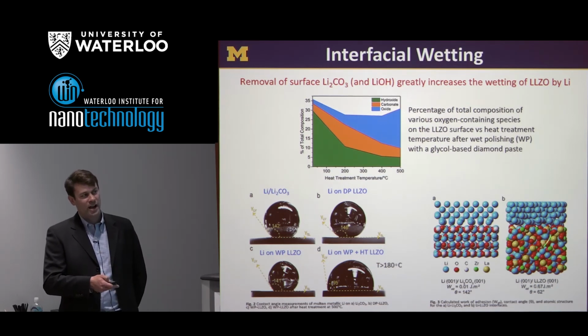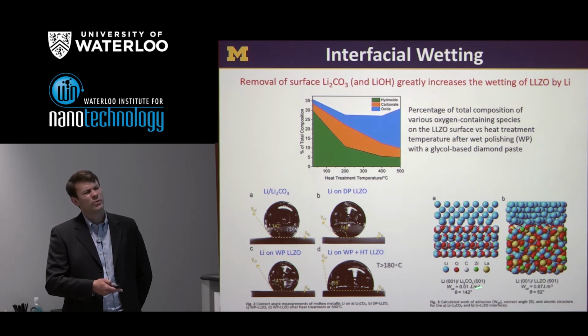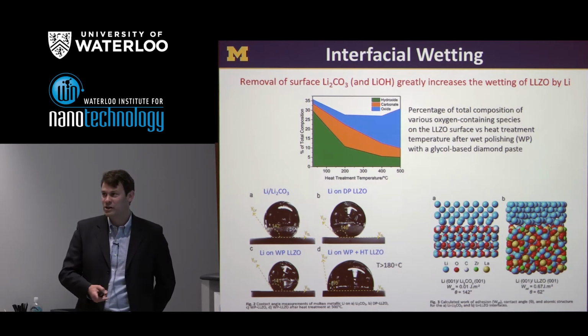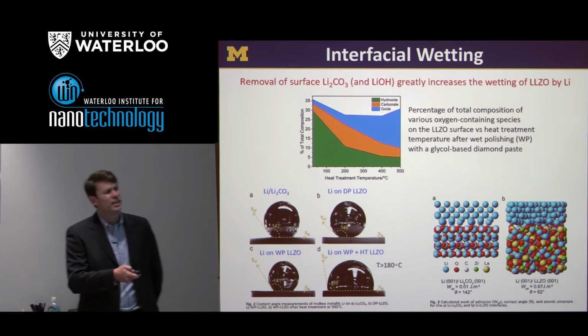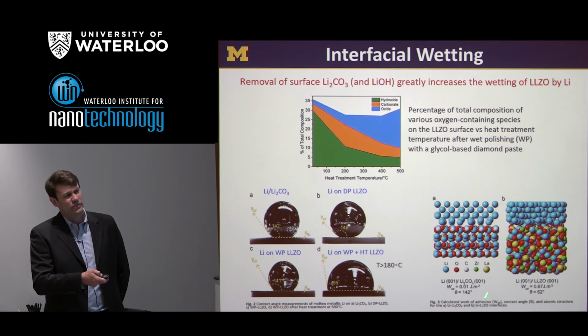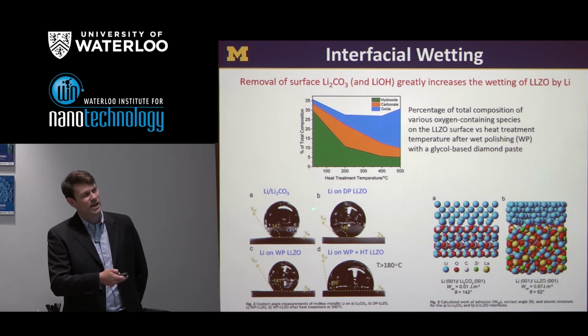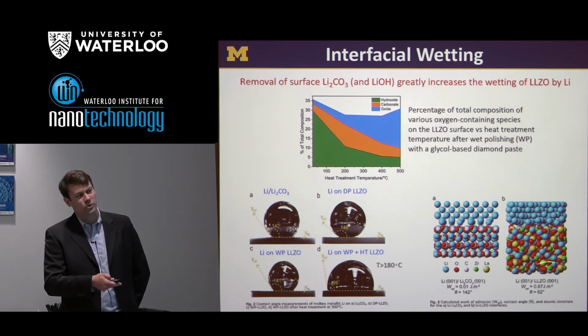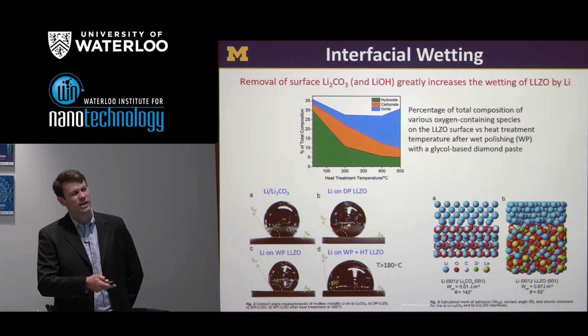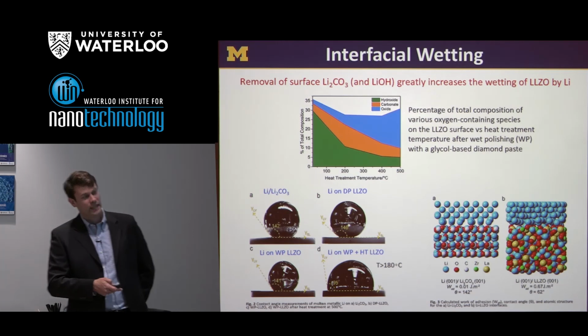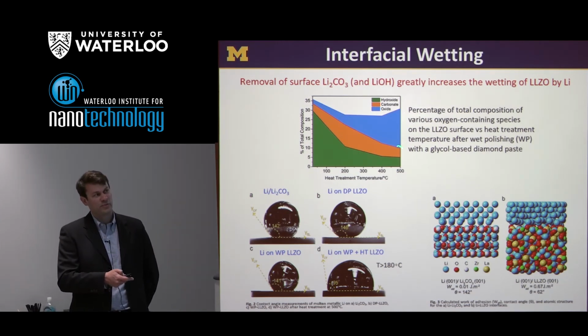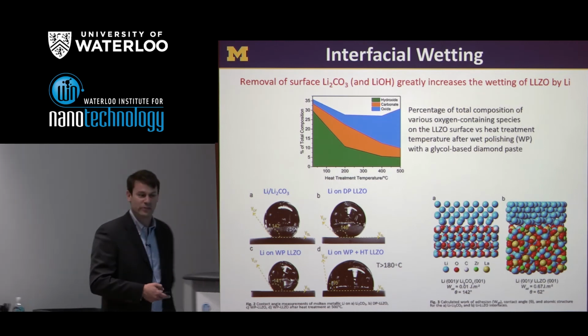This is something we can also calculate, incidentally. By building models of the lithium carbonate or lithium LLZO interfaces, we can calculate the work of adhesion, and then through something called the Young-Dupre equation, we can back out a theoretical wetting angle. You can see we're doing really well with the carbonate wetting angle, about 140, very similar to these 3. And we predict a stronger interaction between pristine LLZO and metallic lithium, giving a 62-degree contact angle, stronger than what's seen here experimentally, probably because even in this system there's still some amount of schmutz on the surface.